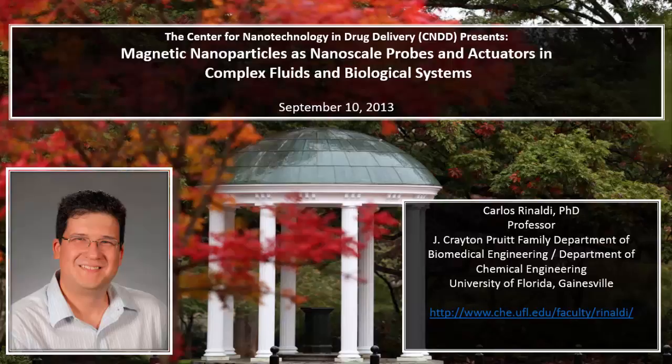Perhaps the best known biomedical application of iron oxide or magnetic nanoparticles is the idea of using them for magnetic resonance imaging, which is approved in the United States and in Europe for use in humans as negative MRI contrast agents. And the important thing about this, the idea that they've been accepted, they can be used clinically, is that at least for the particles that went through this trial, which consisted of iron oxide particles coated with a polysaccharide dextran, we believe that there are no major toxicity issues, okay?